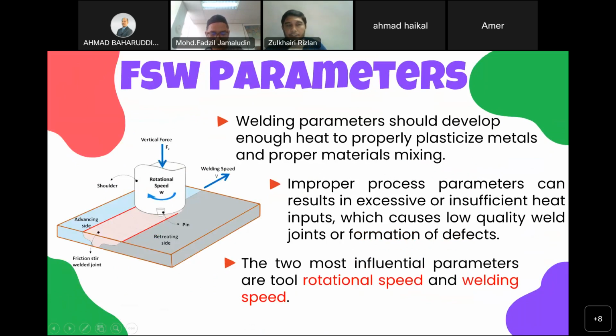Basically, the parameters in friction stir welding should generate enough heat to properly plasticize the material and ensure a proper material mixing. Since improper process parameter can result in excessive or insufficient heat input, which will cause a low quality weld joint or formation of defects. There are many parameters involved in friction stir welding, but based from previous works as well as mine, the two most influential parameters are rotation speed and welding speed.